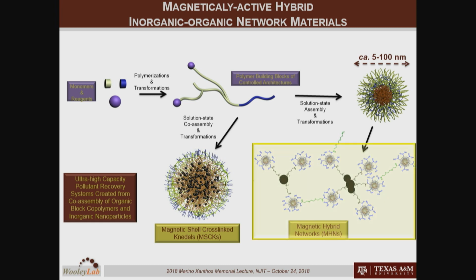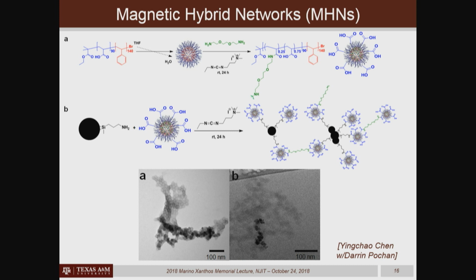And so let me show you what her result was here, where all she had to do was basically take the same kind of block-copolymer that Adriana had been working with and assemble it into micelles in the absence of any inorganic nanoparticles, and then conduct the cross-linking in the shell. And then she could take an inorganic iron oxide nanoparticle that now presents amino groups from the surface, and then she could take some of the residual carboxylic acids here and do a coupling reaction to establish an amide linkage.